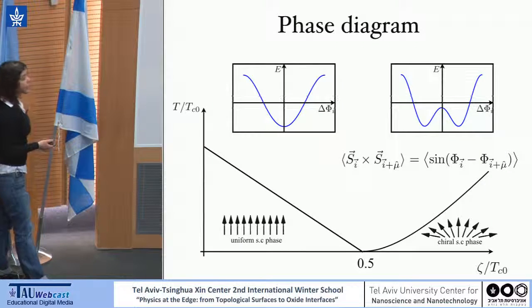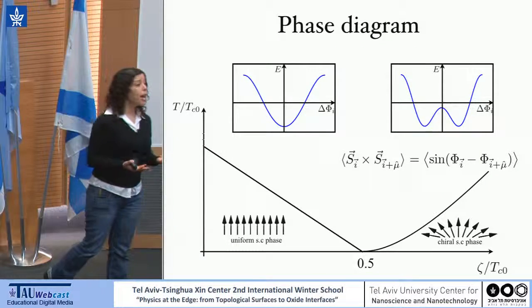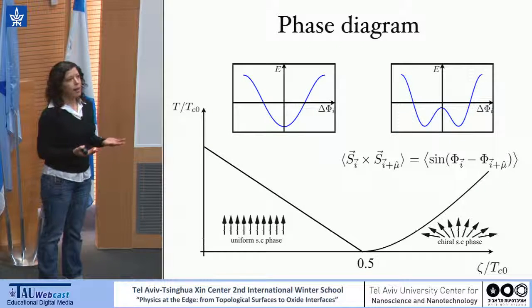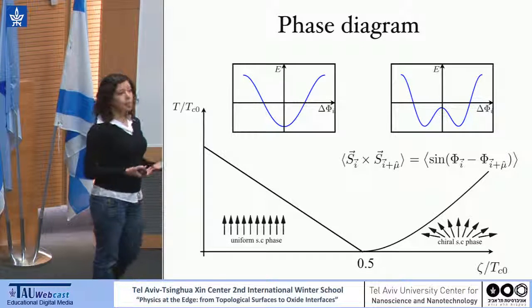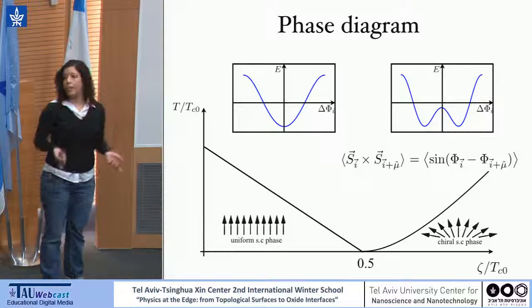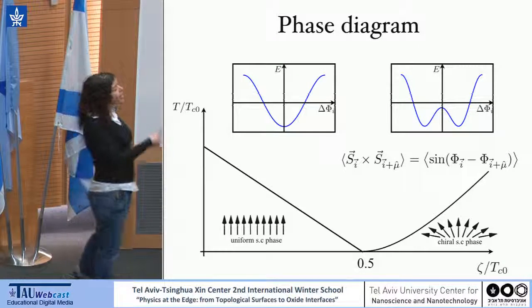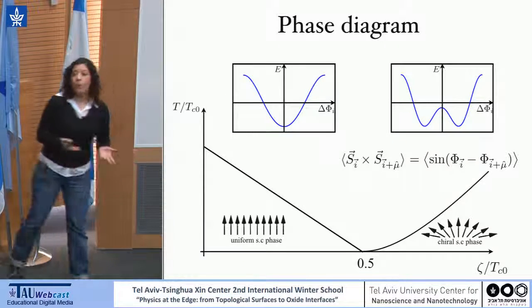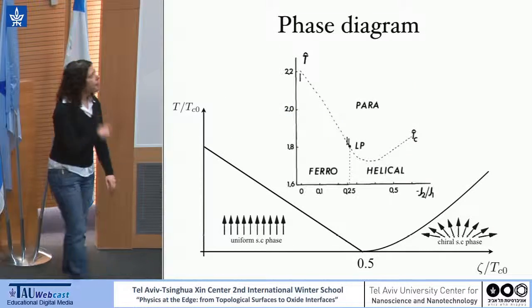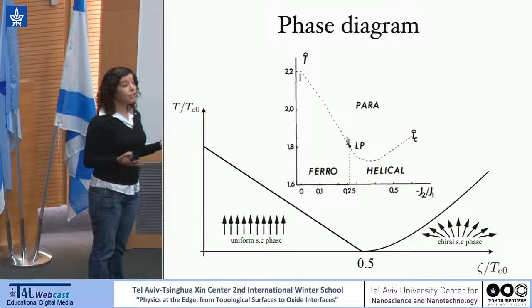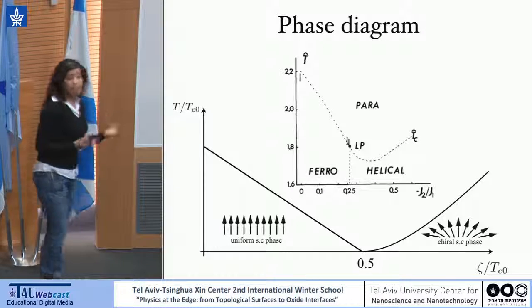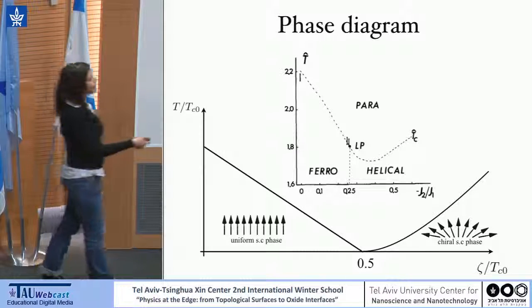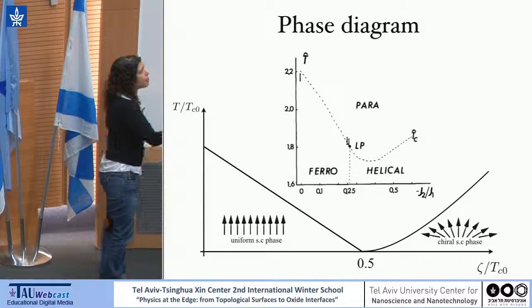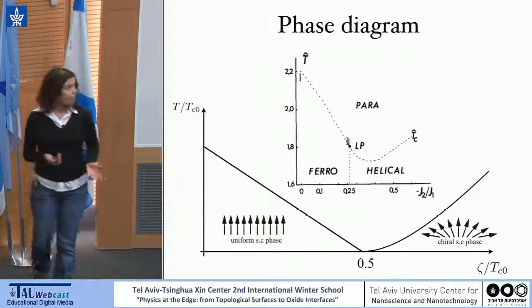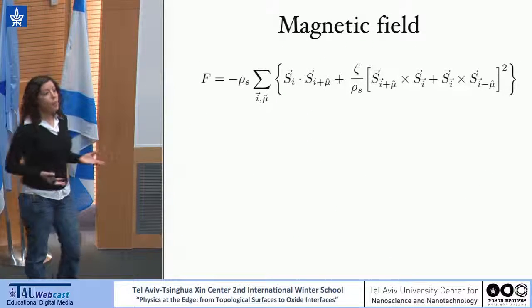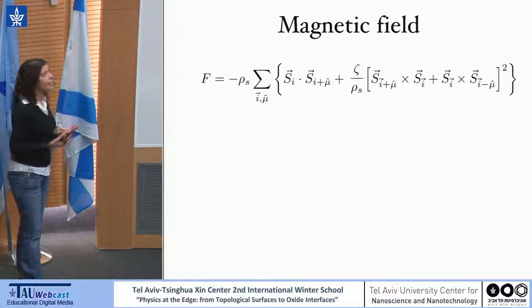Now, what happens in such a system is that in addition to the superconducting order parameter, we have an additional order parameter, and that is this kind of chiral order parameter, where the gradient of the phase acquires some finite value. And the transition in between is just a regular second order phase transition between them. Now, one may see such a transition in a magnetic system, where basically this kind of point, here seen in some other spin model, is what is known as the Lifshitz point.